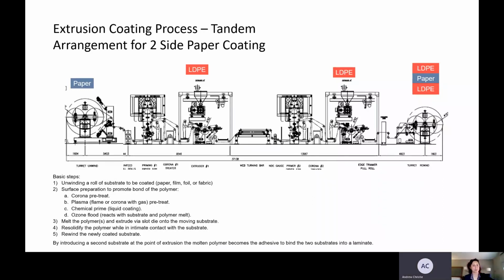So I just wanted to start by reviewing the extrusion coating basics, and I've put up here a slide of a typical tandem extrusion coating line for paper. So this would be similar to a paper cup line. And every extrusion line has some of the same basic components. So we've got some sort of unwind, so we can unwind rolled goods into the machine process. There's usually some surface preparation. In this case, we're showing here a chemical priming. This could also be a corona treated. It could also be flame treated or treated with ozone to promote the adhesion of the polymer that's going to be coated onto the paper for good bond to the paper.